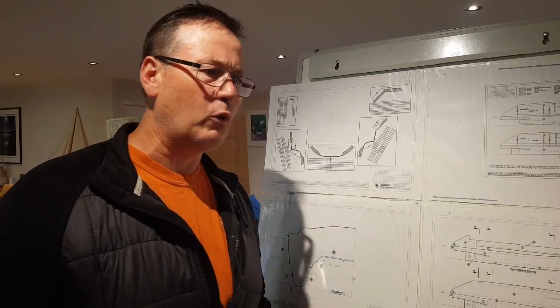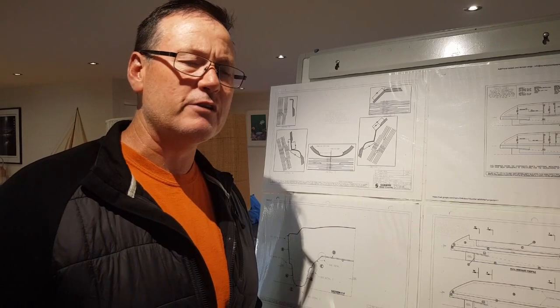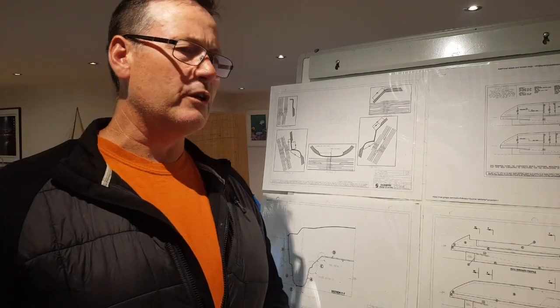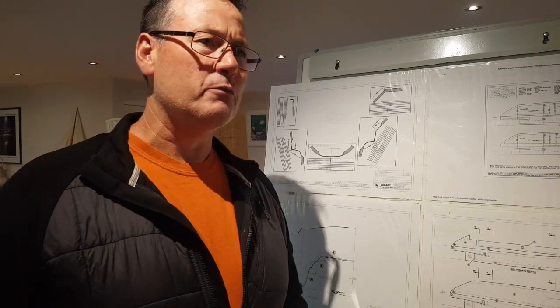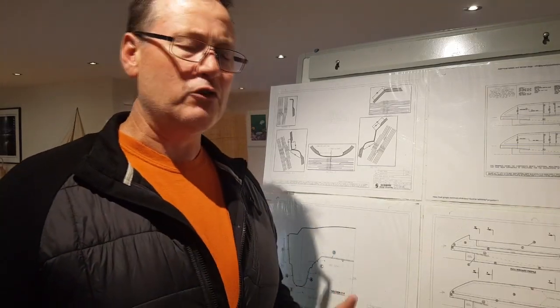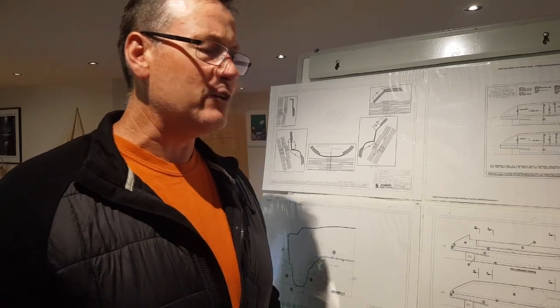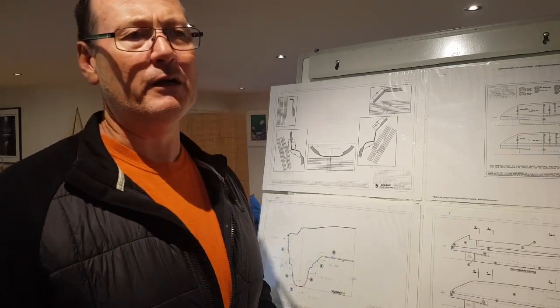We started off with what we call a winter grade vinyl ester, and that is made for the cooler temperatures that we experience here in Jervis Bay in Australia. In winter, it has a slower gel time, so it's around about a 21-minute gel time, just because it gives you good working time, but it allows for the correct catalysation. Now, as we've moved into September and October, we've gone into a summer grade, which has actually given me around about 40 minutes of gel time.